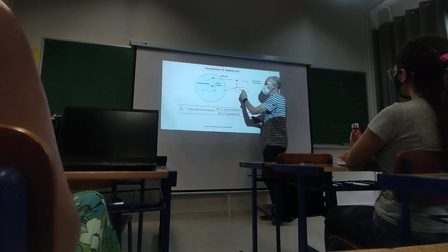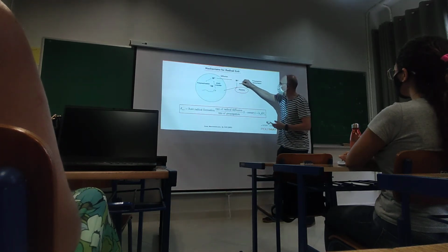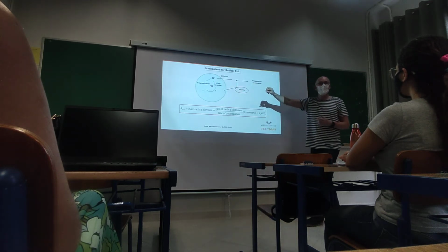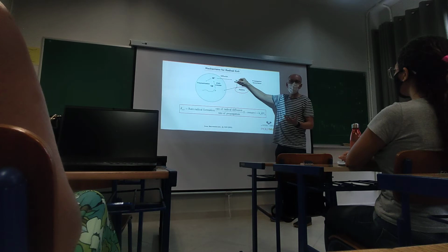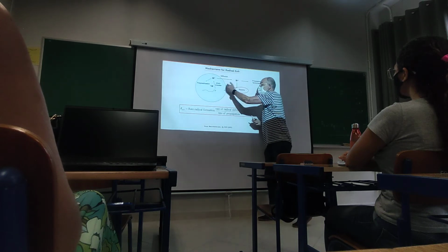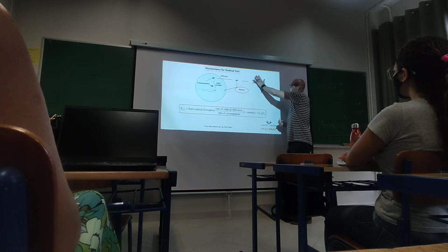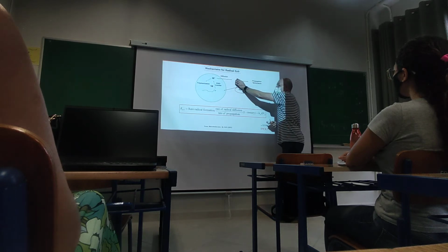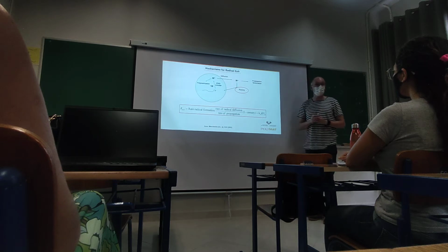Which means that to calculate the net rate of exit, we have to account also for the probability of re-entry. And the probability of re-entry will be proportional to the rate of entry, the diffusion again, divided by the other possibilities that the radical has in the aqueous phase, which are propagation and termination.